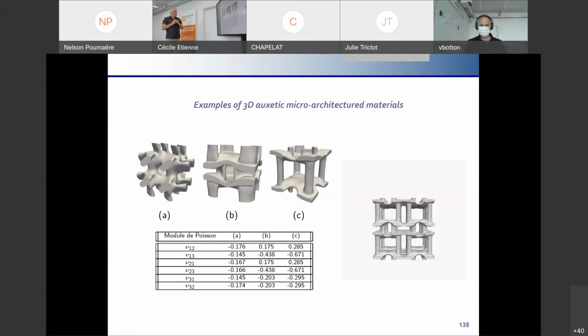However, with such materials, imagine that you prescribe the coarse scale with a negative Poisson ratio, the algorithm finds a solution, and this is what we call an auxetic material. An auxetic material is a material with negative Poisson ratio, and here it depends if the material is isotropic or not. Here we have an anisotropic material, so we can have different Poisson ratios, and some can be positive and some can be negative. Depending on the case A, B, and C, in case A, all the Poisson ratios are negative.